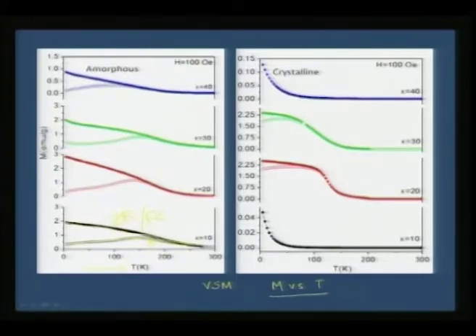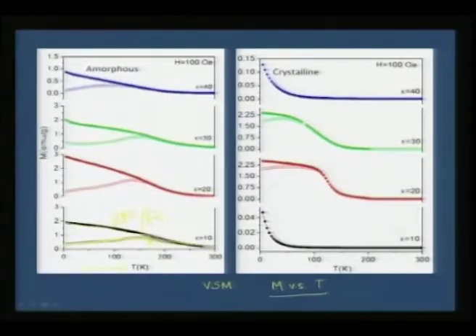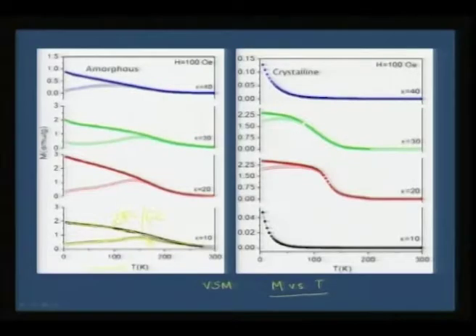So if you do not cool your sample in magnetic field, then you see this sort of antiferromagnetic interactions dominating the ferromagnetic ordering. But if you cool the sample in the field, which is called field cooled, then you can see here that it is turning ferromagnetic, and this is not there only for x is equal to 10. You also see the same trend for x is equal to 20, 30 and 40. So irrespective of any composition, you see iron platinum amorphous alloys are magnetic across the doping concentration.